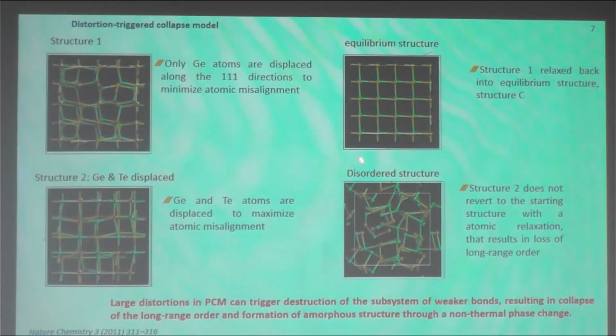germanium atoms, then the structure can transform back to the initial structure, so it relaxes back to the equilibrium structure. But if you have a high distortion in the system, then the system cannot relax back to the initial state, and so it transforms to the disordered structure. So large distortions in PCM can trigger this destruction of the subsystem of weak bonds, and this results in collapse of long range order and transformation to the amorphous phase.